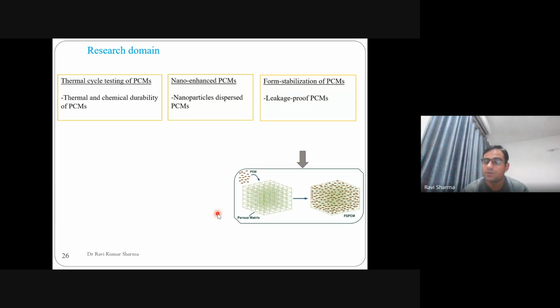For form stabilization, what we do is take a porous matrix, or porous material. Into the pores of this material we add PCM through a rigorous mixing process. Once this PCM settles into the pores of the porous material, after getting melted, the PCM remains in the pores. What you see on the right hand side is called FS-PCM, form stable phase change material. So when the material melts, the PCM is retained in the pores. It doesn't flow away, it doesn't come out of the material. Because of that, it is known as shape stabilized, since it keeps its shape retained, or form stabilized, since it keeps its form very much stabilized.